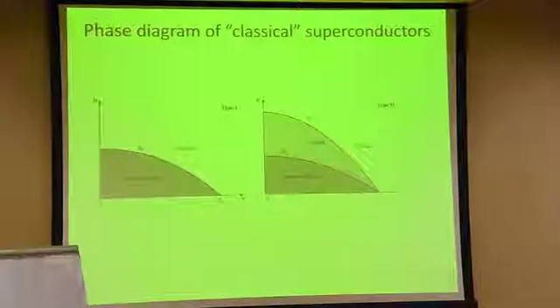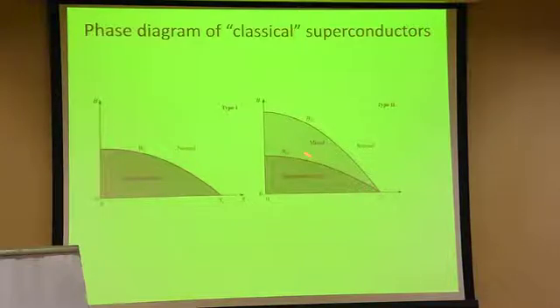Okay, if we look at the classical superconductors, why I'm saying classical, we're talking about the superconductors which were discovered before the pnictides, and that means the low Tc superconductors. So for type 1 superconductors, we have a phase diagram in which we have here Tc at 0 field, and we have a critical field which depends on the temperature, and this region is the superconducting region. This one is normal. If we look at type 2 superconductors, as I said, we have two critical fields. Both of them depend on the temperature. This is the lower critical field, and this is the superconducting phase or Meissner phase, and this is the mixed phase, which is between BC1 as a function of temperature and BC2 as a function of temperature.